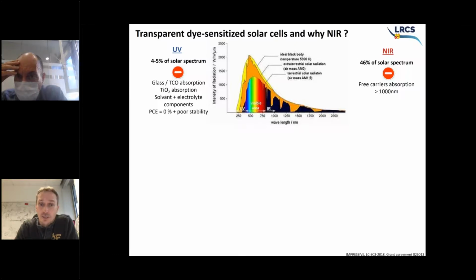TiO2 is a very good photocatalyst, as all of you know. So it absorbs very efficiently the UV part of the light, and unfortunately, I would say the solvent and the electrolyte components are also very strong UV filters or UV absorbers. So if we want to develop a UV dye solar cell, I think that the efficiency will be extremely close to zero, and the stability will also be very poor, meaning that you will excite directly the band gap of titania, and then the holes that are located in the titania are very oxidizing.